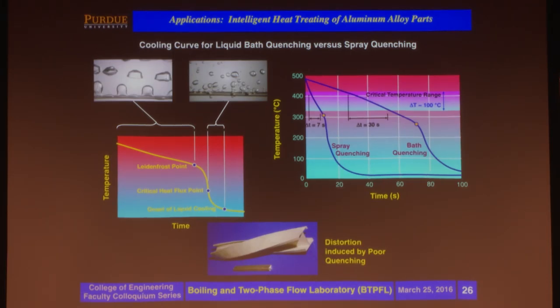There is absolutely no control over the cooling process. You get distortions, cracking, and they live with that sometimes. Or they throw away the parts that are deformed more, and they keep the good ones. And this is really the type of shape that you get. This is about 2 feet in length, and you can see an H shape completely distorted as a result of poor cooling. So what we're doing is replacing this, what we call bath quenching, with far more effective spray quenching.